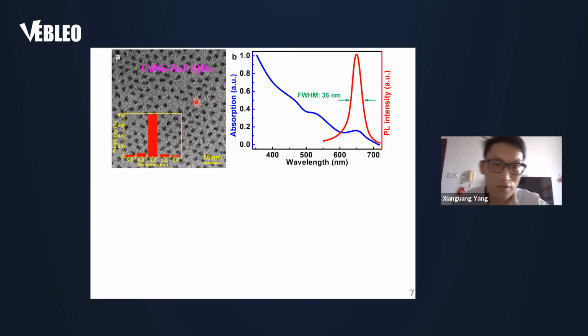Here we give the TEM characterization of the experimentally used quantum dots. The histogram shows that the average diameter of quantum dots is about 6 nanometers. And figure B shows the optical properties. The blue line shows the absorption of quantum dots, and the red line shows the emission properties of quantum dots with an FWHM of 36 nanometers.